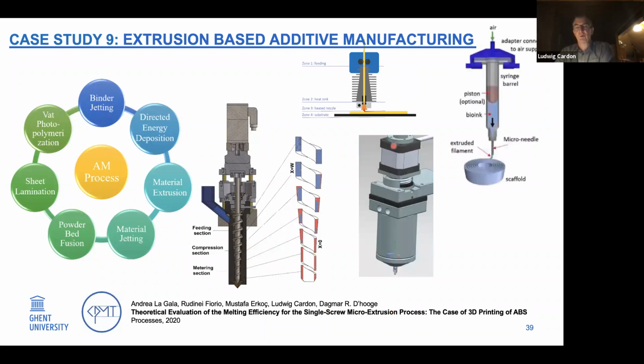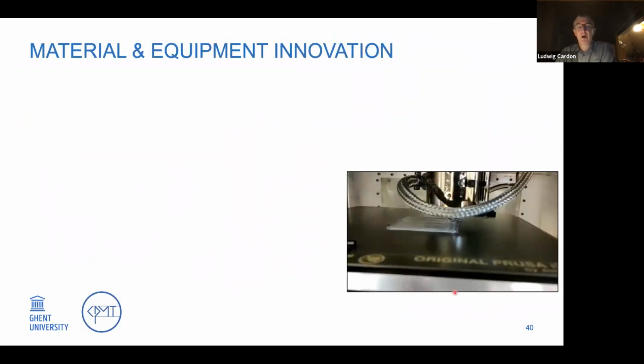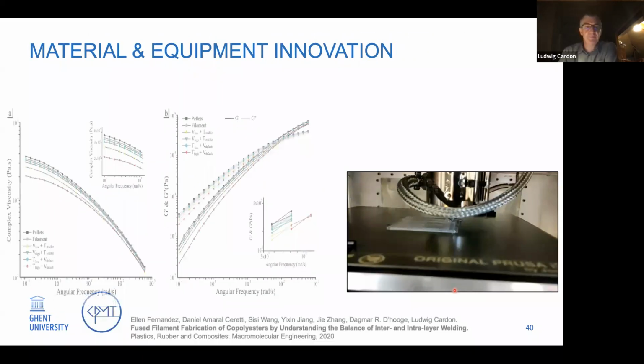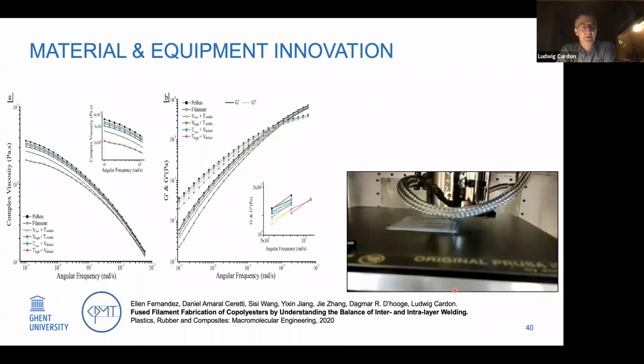So we also tried to combine that with the so-called syringe 3D printing, where you have a liquid inside a vessel and with a kind of hydraulic or pneumatic piston system, you push the material out of your nozzle. So in that case we investigate the different kinds of rheology of, on one side, the pellets. You can see them here on the left side. So we analyzed the flow behavior of a pellet. We analyzed the flow behavior of a filament for different mixtures, and then find out what's the best opportunity.